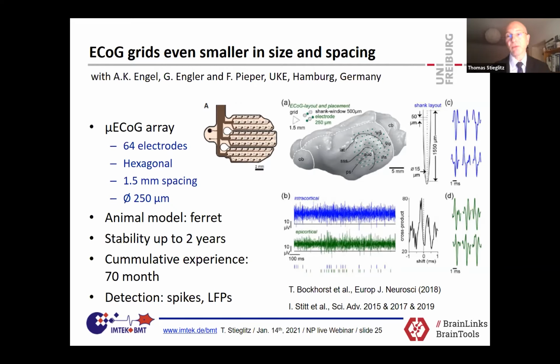And that means you do not necessarily need amplification circuitry, electronic amplifiers directly integrated in the array, but if it really sticks well to the surface, you're able, by switching the bandwidth during recording, to get either local field potentials or spike-like activity that corresponds well here to multi-unit activity seen with intracortical probes. The blue spikes are intracortical, the green ones are recorded over this array.